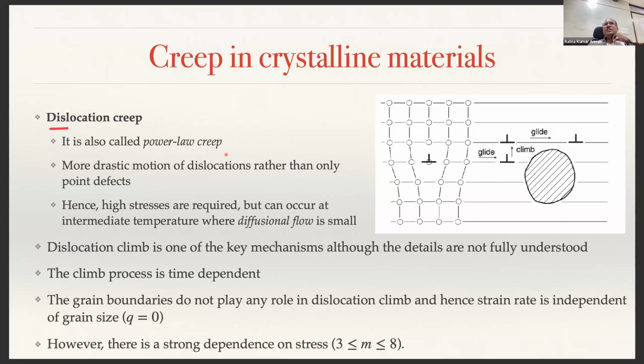The other one is dislocation creep. It is also called power law creep. What happens is that at very high temperature, you will have a drastic motion of dislocations because of the additional energy provided by the high temperature. This can happen at very high stresses, but at intermediate temperature, where diffusional flow is small. When diffusion is very small, dislocation creep can still take place if your load is very high, even though temperatures are small. So, dislocation climbing.